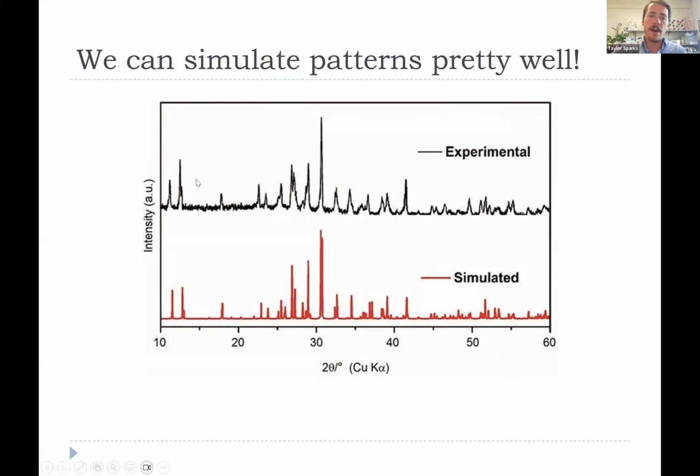You will have an experimentally measured data set. That's the black data points here. If this is your first time seeing X-ray diffraction, it's probably not, but you know that it's intensity plotted as a function of diffraction angle 2 theta, and these peaks are indicative of where you have Bragg scattering happening by satisfying Bragg's law. They're not perfect line functions. There's some broadening that comes from the instrument and other things related to the size of the particles.